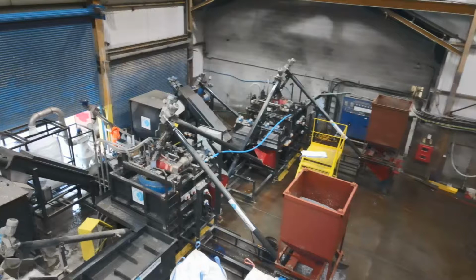And what is unique about our system, unlike other active separation systems whereby you're scanning or trying to select the correct component for purification, is that our system does two things. First of all, the material is driven into the center of the stack to oscillate, and this drives the separation between PP and PE up to 98%. But what we can stand over and guarantee is that the 2% that is contaminating the polypropylene is in fact only polyethylene. All non-polyolefins have been removed.